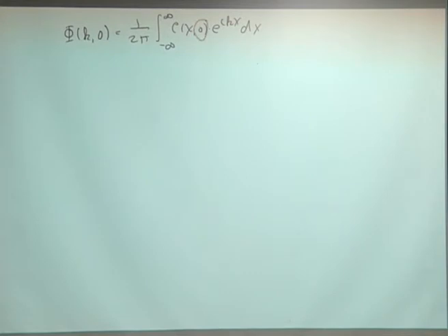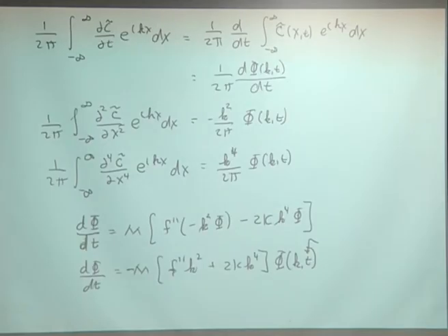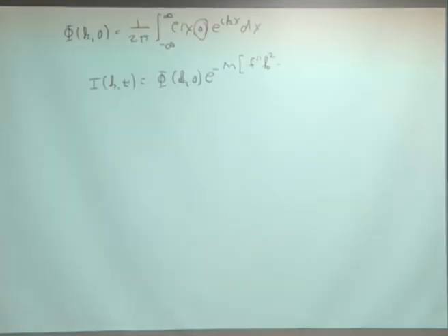And so now that you know what the initial condition is, you can solve this differential equation here. It's just an exponential, and you know what the Fourier transform is at time t equal to 0. So you just get ik times time. And now with the Fourier transform, you can write the inverse transform and determine exactly how this function, how the fluctuation, will evolve in time.